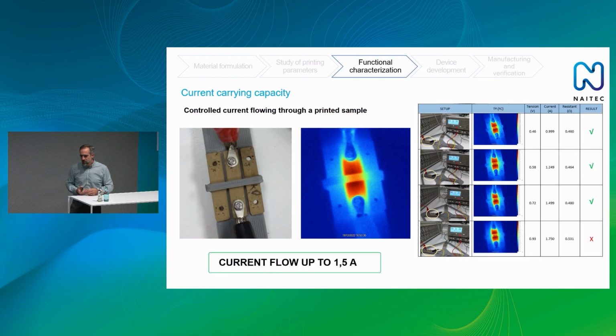After we have found the best conditions for printing, we started doing some functional characterization. We wanted to know how much current this filament can withstand, because having a polymeric part is critical, and it might degrade with high current due to temperature. And we have tested it, and we can see that with currents of up to 1.5 amperes, the resistivity of the material doesn't change, so it's still functional as printed. If the current is over that, the resistance starts to increase, so the material is being damaged. But we are happy that the current that this material can withstand is quite high, actually, for polymer-based filament.